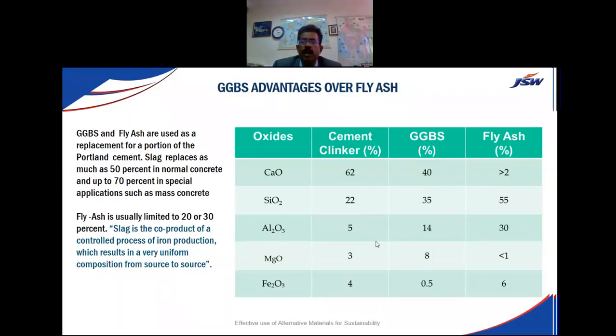Al2O3 is also up to 14%, and in cement it should be controlled to 5%. Here in fly ash it is 30%. So this is the main product, calcium oxide, which is really helping the GGBS to perform, because GGBS has 40% calcium oxide.